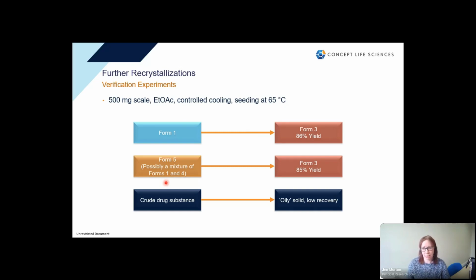Chemists will be familiar, I guess, when you look at something and it's looking quite turbid and you think there might be some solid, and then you go to filter it off and it all goes to a bit of a nasty slump on the sinter. Oily solid, gum, and a low recovery. So what we have to conclude there is that our impurity profile is playing a large part in the success or not of this recrystallization.